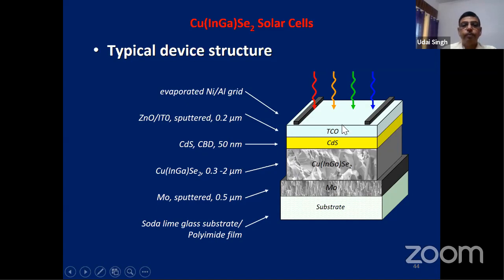It's a thin layer. Then you have a transparent conducting oxide, because light has to pass. It should be conducting also, and light has to pass, because you know there is a trade-off between these when you are trying to make a transparent conducting oxide, which are also used in your mobile smartphones, because when you tap, you can see the numbers and all this. So it should be transparent and also conducting. There is a certain trade-off, because if you use a direct metal, no light will be absorbed, all will be reflected back. So a transparent conducting oxide is used, and if it is a slightly large area, you try to put a certain grid so that you can collect the current from all over the area.